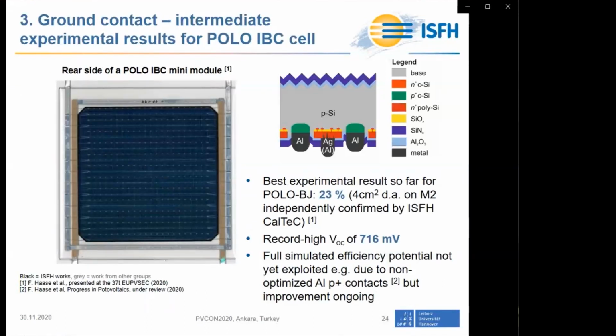Also for this cell structure, I would like to establish the ground contact by showing our recent experimental results. We obtain 23% for an industrial processed M2 wafer, but still designated area measurement. The reason why we have not yet exploited the full efficiency potential is similar to that of the POLO back junction cell, that we are still working on the improvement of the aluminum p+ regions. On the left-hand image, you can see a photograph of the rear side of a mini module made of POLO IBC cells with a multi-busbar interconnection.